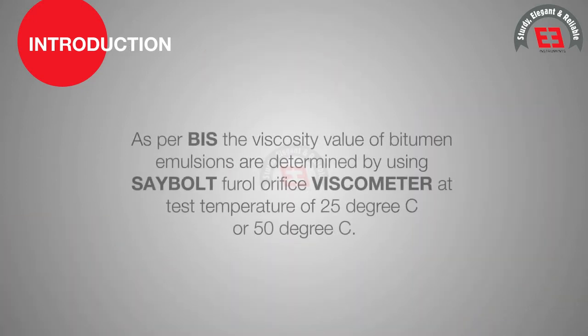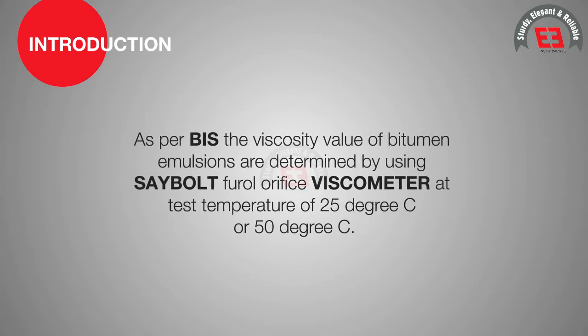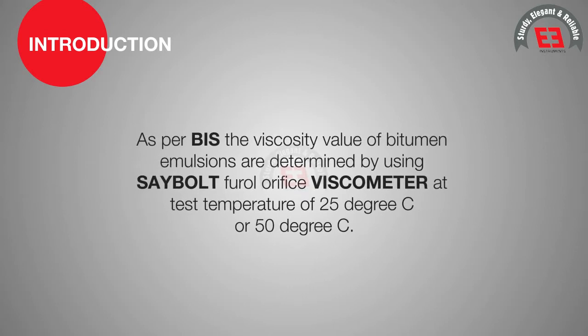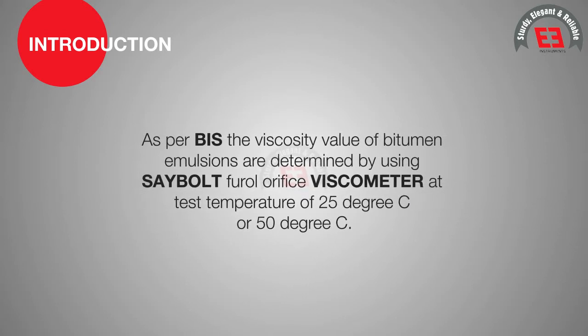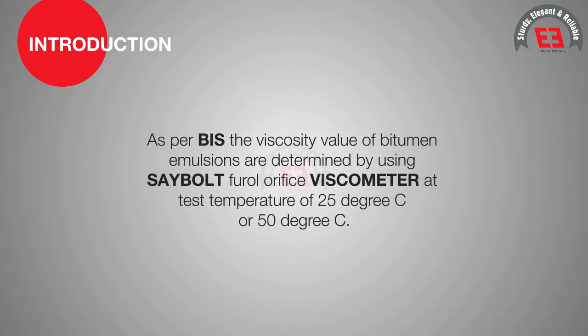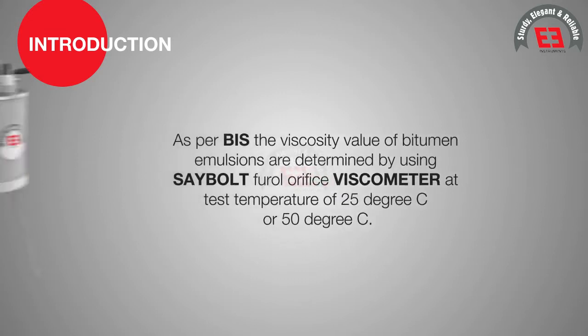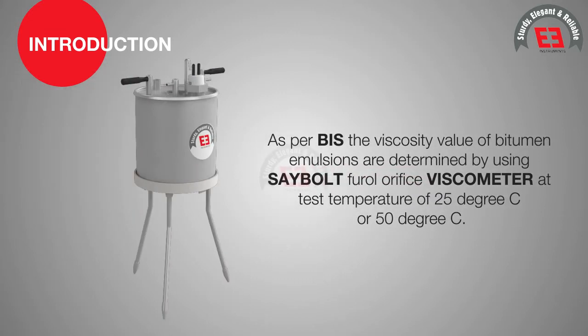As per BIS, the viscosity value of bitumen emulsions is determined using the Saybolt Furol Orifice Viscometer at a test temperature of 25 degrees Celsius or 50 degrees Celsius.